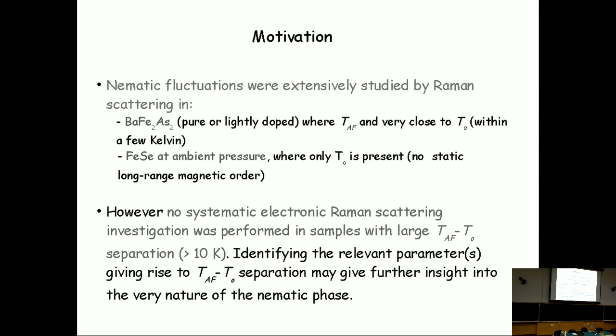And then comes the motivation for our work. When we started working on that, we saw that the nematic fluctuations were already extensively studied by Raman scattering in the so-called 1-2-2 systems, BaFe2As2, either pure or lightly doped, where T_AF, the temperature of the antiferromagnetic stripe ordering, is very close to the orthorhombic transition temperature. They may be separated by 1 or just a few Kelvin. And also iron selenide has been studied by Raman scattering at ambient pressure, where only the structural transition temperature is present, but no static long-range magnetic order.